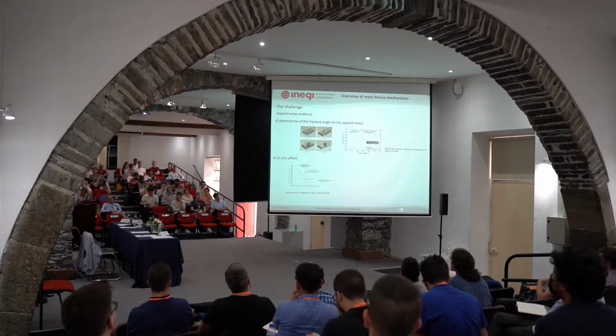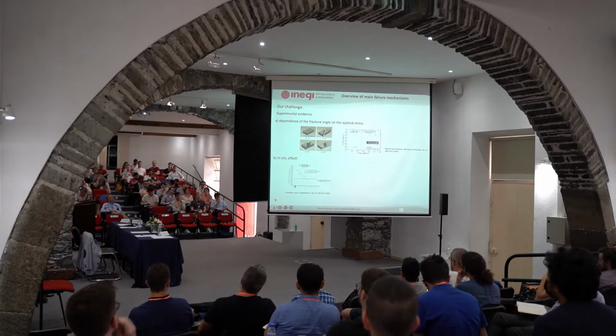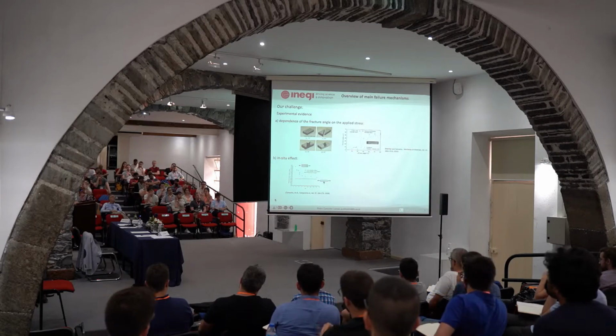So the other thing that is often neglected in the analysis of composite materials or in the failure analysis is what we call the in situ effect. That is, I think, easy to understand if we look at this picture. So basically here we have the number of 90-degree plies that are clustered together, or in other words, the thickness of a 90-degree ply block as a function of the stress that we need to apply to create a transverse crack. So here, this continuous line corresponds to the UD strength, okay?